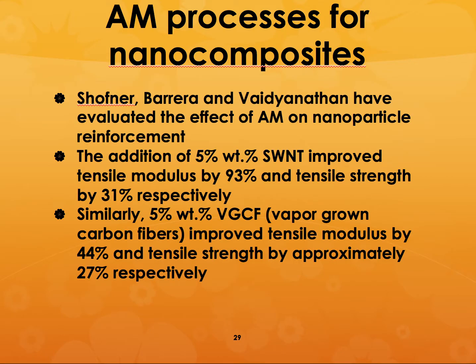I was part of a group from Rice University that looked at the effect of additive manufacturing on nanoparticle reinforcement. And just 5% addition of single wall nanotubes. SWNT is single wall nanotubes, and MWNT is multi wall nanotubes. So, those are two different types of nanotubes, and this was done in the early to mid 2000s. And we found that just adding 5%, but adding 5% is a lot, improved the tensile modulus by 93% and tensile strength by 31%.